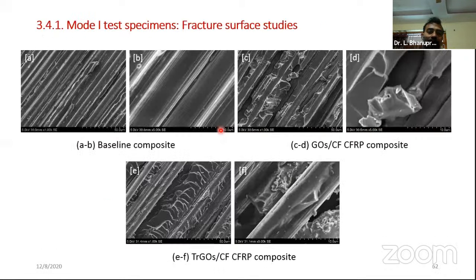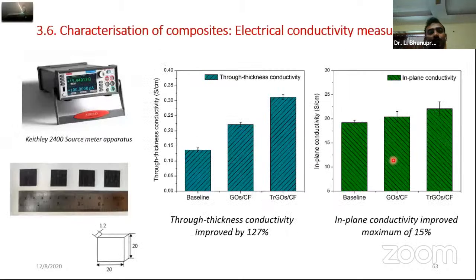So in each and every case, we have noticed very good improvement, but the fracture is slightly different here because the matrix is plain. It is not a matrix modified one, but the fiber is being modified here. So you can see the crack that is being developed on the epoxy. This is a plain epoxy, so you can see the step kind of cracking. If it is filled with a nanofiller, you can expect a different kind of failure. But wherever fiber surfaces are there, the matrix is tightly bonded. You can see with the TrGO coated carbon fibers, very good adhesion. And in this particular case also, the matrix has been tightly adhered with the fiber surfaces. So that is very clear here from the fracture surfaces.